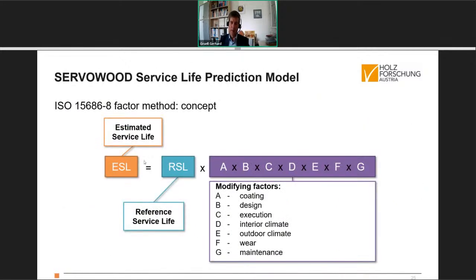From all the results of SERVOWOOD, a factor model for service life prediction according to this ISO standard was drafted, where an estimated service life is calculated from a reference service life multiplied by a series of factors. And the interesting thing here is that the reference service life is the service life of a product which you know very well, where you have real experience from practice. And the interesting thing is that here you can really bring in long-term experience with long existing products and compare them to a development product by applying these factors. And then you get an estimation of service life relative to the reference system.